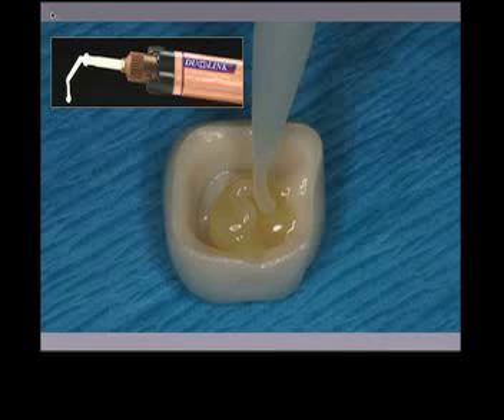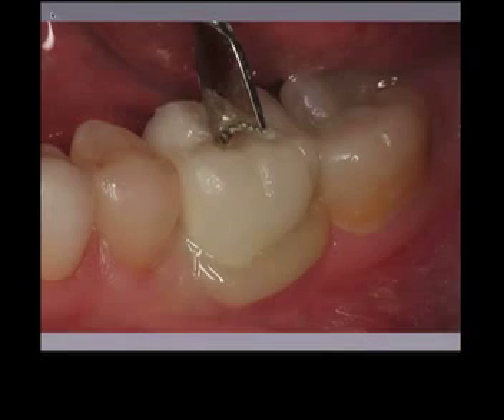So then you want to seat that with even pressure, allowing the excess cement to extrude, and wipe away the excess. Don't immediately floss through the contacts. I find that it may interfere with the bond formation. We certainly don't want to do that. After about 30 to 60 seconds, we can start moving this bulky material away.